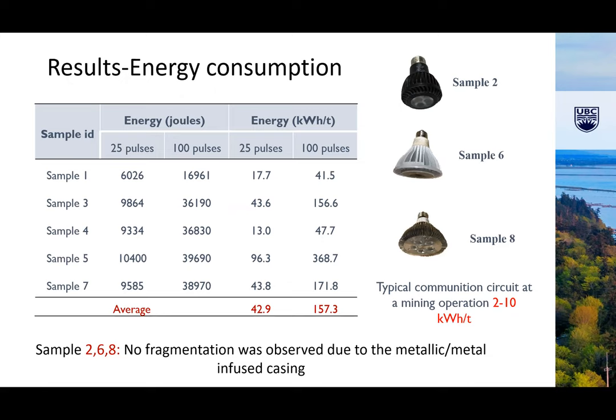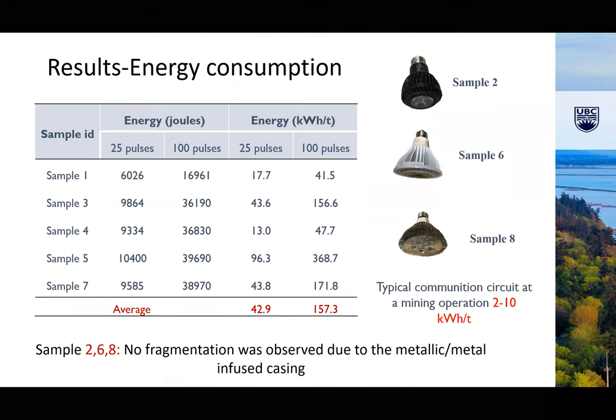When we look at how much energy was used and the energy efficiency, you can see quite a huge amount of energy on average: 42 after 25 pulses and 150 when we used 100 pulses, averaged over all the lamps, those that the technology worked for, and others not necessarily. Samples 2, 6 and 8 were not disintegrated. By comparison, a typical comminution circuit would only use 2 to 10 kilowatt hours per ton. So the energy used is formidable for a continuous system.